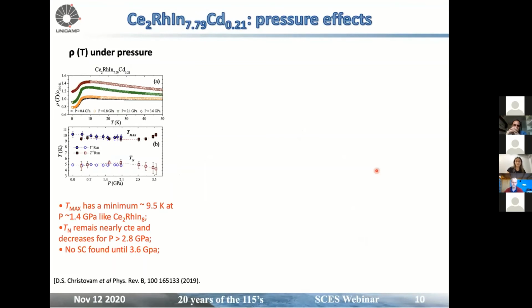We studied that same cadmium compound as a function of pressure. So those are resistivity measurements, and if we put both Tmax and Néel temperature as a function of pressure, we could see that Tmax has a minimum on the curve around 9.5 Kelvin and 1.4 gigapascal, and TN remains nearly constant, but no superconductivity was found up to 3.6